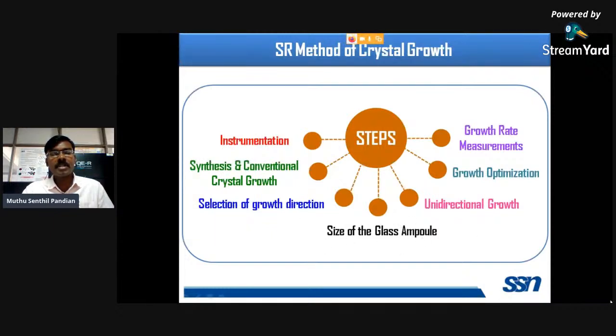It depends upon the solubility of the material. If it is a low soluble material, we have to select a very low ID, inner diameter. If it is a highly soluble material, it can be easily grown. So we have to select a large size glass ampoule for the bulk growth, unidirectional crystal growth and growth optimization.